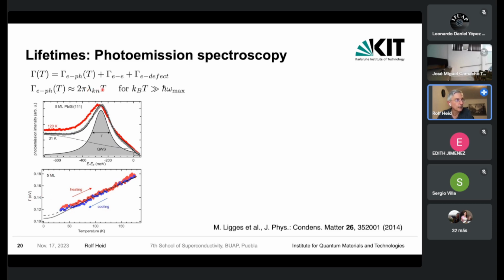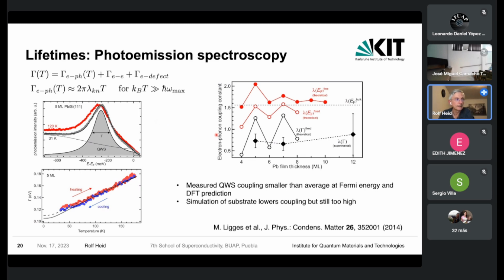And one can show that the line width contribution coming from the electron-phonon interaction should have a linear temperature dependence. And the slope of this temperature dependence is essentially proportional to the coupling constant of this individual electronic state. So from this type of experiment, one can extract directly the corresponding coupling constants. And that has been done, and these are shown here by the full diamonds. And we have also then tried to compare that with calculations based on these specific states at the gamma point as has been measured here.